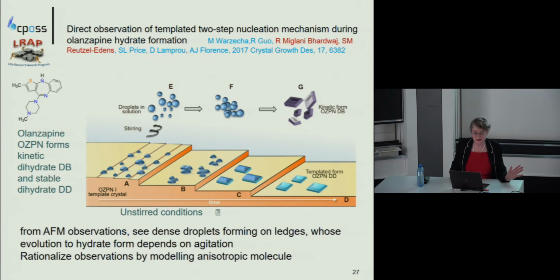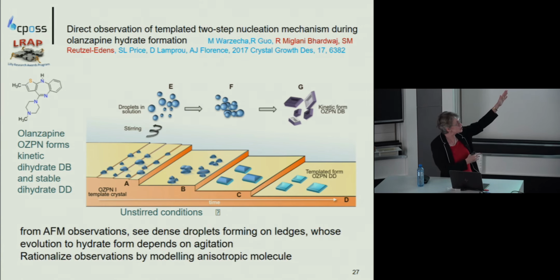So more recently, we've been looking at the nucleation by AFM, and there are some rather surprising results: if you put olanzapine in water, it will hydrate and form the hydrates. But you could see in the AFM that you're getting hillocks growing at the ledges in the olanzapine surface. If it's under stirred conditions, then the droplets detach and form the kinetic metastable dihydrate polymorph. If it's left nice and quietly under the AFM, you can see it crystallize into oriented crystals of the more stable dihydrate polymorph.